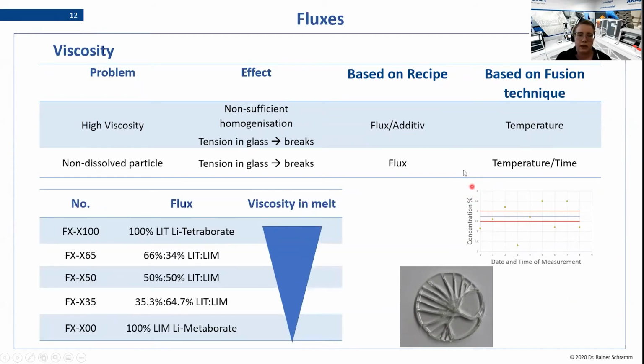So how can I tackle this problem with my flux? We already saw that the viscosity in the melt decreases with increasing metaborate part. So the more metaborate is in my flux, the less viscous it will be in the melt. So the homogenization will be easier for a machine or a human to do, and it will also be easier to dissolve the sample in the melt.